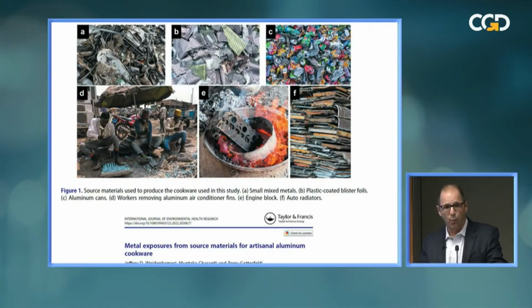And so you may ask yourself, where does the lead come from in aluminum in the first place? Why are we concerned about it leaching into our food? This work was from Wiedenhammer and Perry Gottesfield, who's here today, some 10, 12 years ago, who found that the feedstock for these aluminum cookware are not just Diet Coke cans, which would be nice, but aluminum engine blocks, radiators that are potentially soldered together with lead solder, cans with lead solder, and also used aluminum cookware. In addition to that, electronics. So everything goes into a big pot, and if it melts, it can be formed into an aluminum pot or pan, specifically in lower and middle income countries.